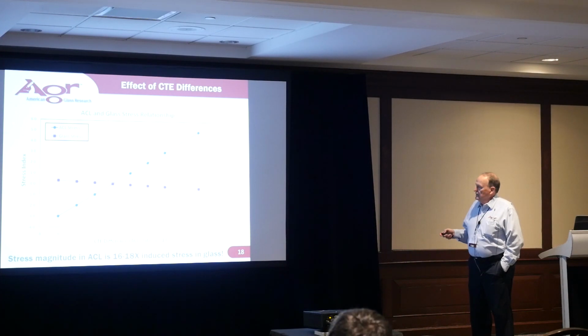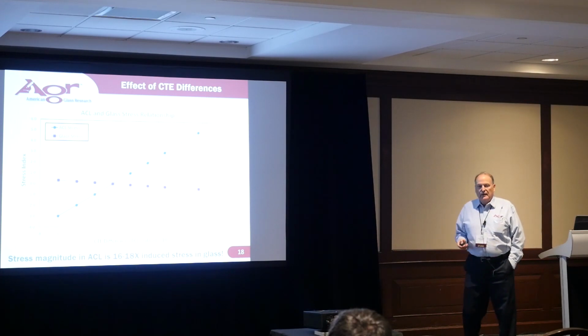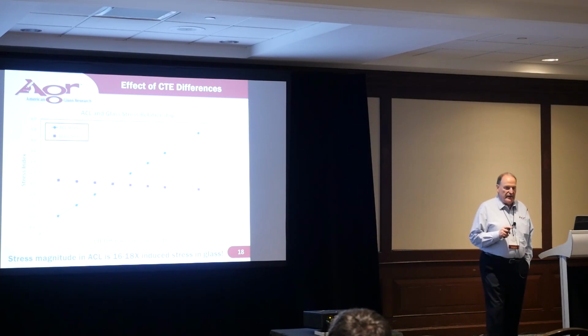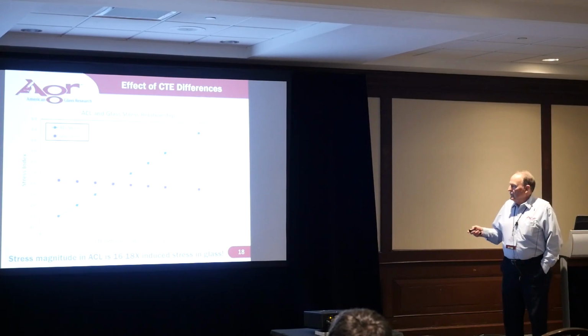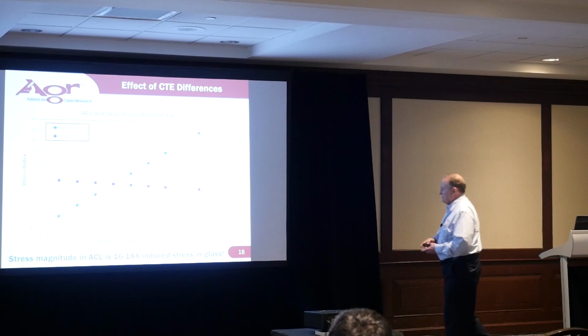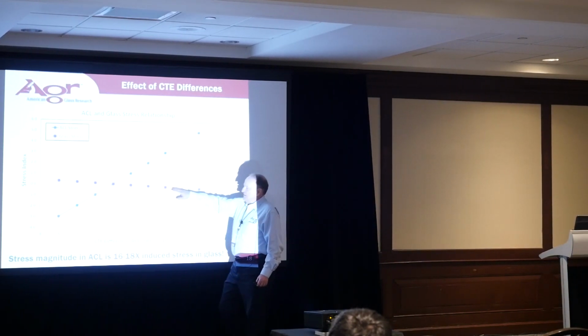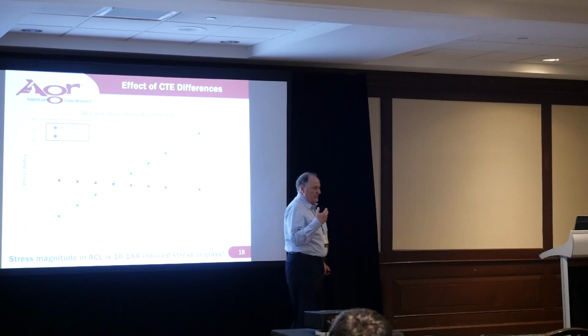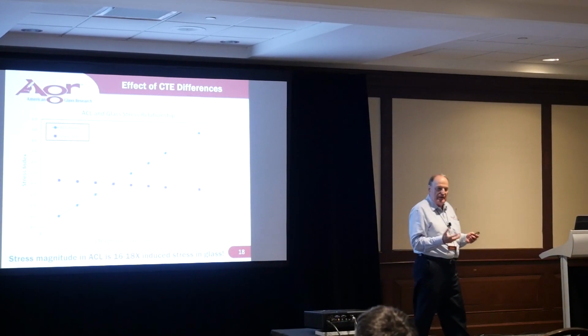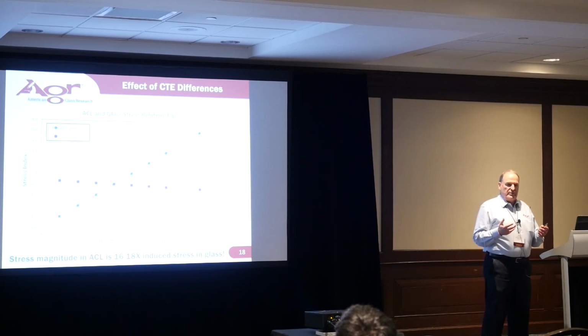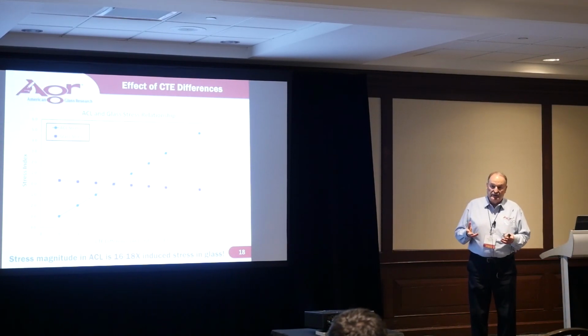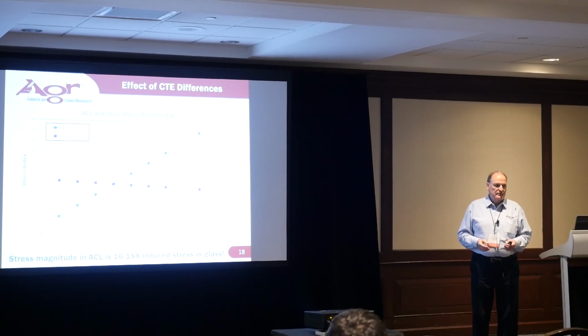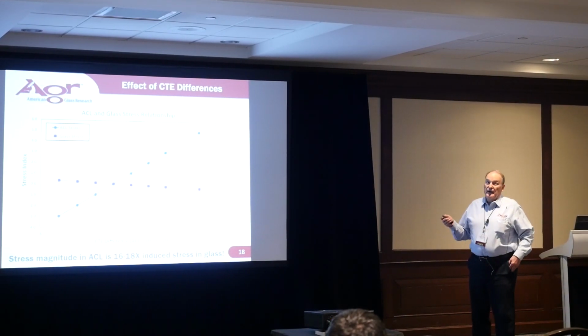Here we have coefficient of expansion of the ACL larger than the glass. We have tension being generated in the ACL, compression being generated in the glass underlying. Now, remember one of the assumptions that we made way back when. We can measure this stress. The stress that's in the glass can easily be measured. And we don't know what the stress was in the ACL, so we had to make the assumption that it's going to be about the same magnitude, opposite in sign, and maybe a little bit higher. Well, as it turns out, it's quite a bit higher.